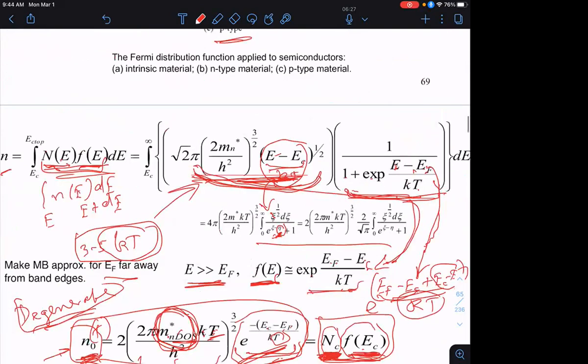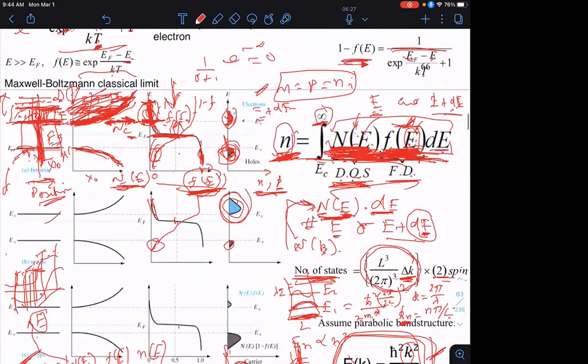And when I say mapped, I don't mean integrating all these density of states and calling that the effective density of states. Instead, I weight the allowed states by the corresponding occupancy factors. So as someone correctly pointed out, higher lying states count less heavily than lower lying states. So that weighted sum is what I call my effective density of states, times the occupancy factor no longer as a function of energy. I multiply that by the occupancy factor F of EC at the conduction band edge. So that's also a single number, okay?